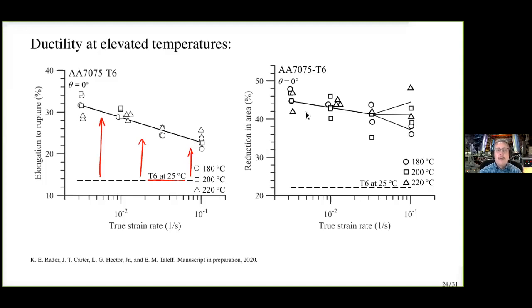Okay. Reduction in area, another measure of ductility. It's showing a similar behavior. It's very good at elevated temperatures, but we're also getting the same sort of reduction that we saw before as we go to faster and faster strain rates. So we have to be a little bit careful how fast we form. That's the headline of what we take away from this. Okay.